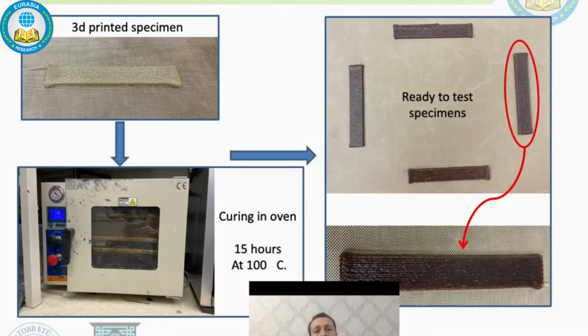After all the samples are printed, all the samples are cured in an oven. As I mentioned before, there is a repeated melting and cooling process in thermoplastic printing methods like fused filament deposition or etc. But in direct ink writing, there is just one heating process after printing called curing. This curing process at the very end offers stronger bonding between printing lines and layers.